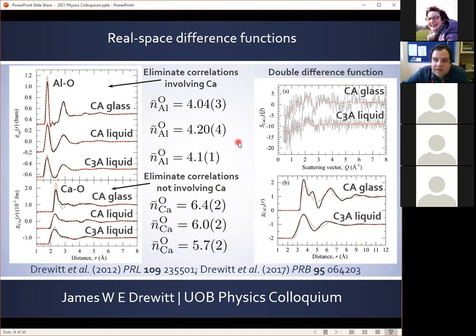We could take this one step further still, and because we have three structure factor measurements, we can combine all three in such a way that we can eliminate all other correlations aside from calcium. And so here we can directly obtain the calcium partial structure factor, and here the calcium pair distribution function. And in fact, this represents the first application of neutron diffraction with isotope substitution to obtain a partial pair distribution function for an oxide melt, here for C3A liquid.